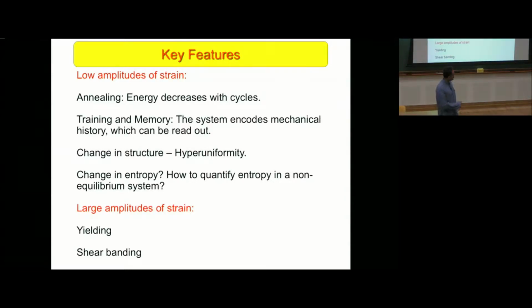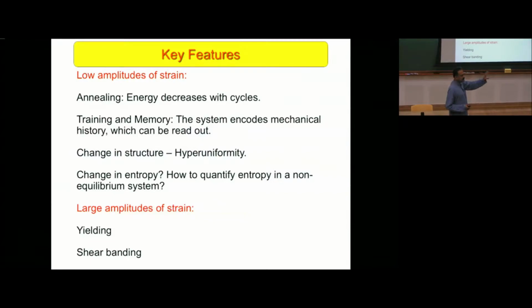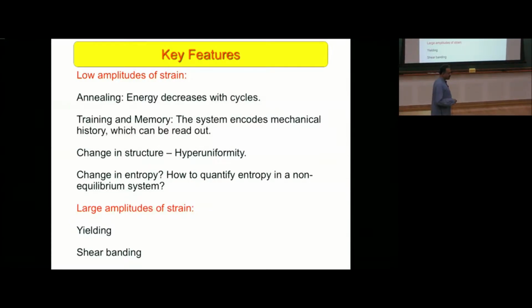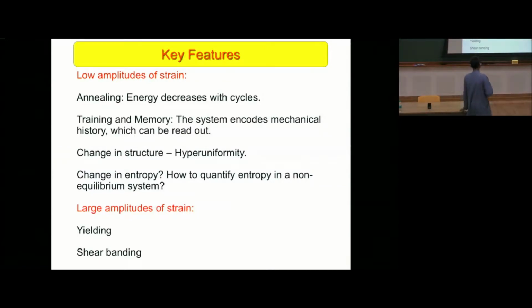Sure. Now, I'll run through these quickly because there's a little bit of an aside. But before I start talking about shear bands, I wanted to say some interesting things associated with this transition. I already mentioned annealing, and something that we've been looking at quite a bit, which I won't say more than one slide's worth of, is memory effects. As I said, the system with a number of repeated cycles reaches some steady state that recalls memory of what you did to it. The structure of glasses changes in interesting ways below and above the yielding transition. They exhibit this property called hyperuniformity, and there are also some interesting changes in entropy, which we try to characterize for this non-equilibrium system.